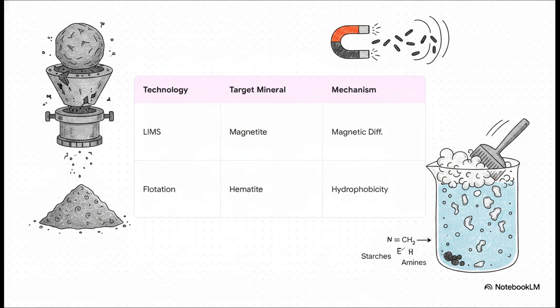Once it's ground into a fine powder, we have to separate out the iron. If it's magnetic magnetite, we just use low-intensity magnetic separation to pull it out. But for non-magnetic hematite, well, we use a brilliant physicochemical process called reverse cationic flotation. We mix the ore into a watery pulp and add highly specific chemicals. We use starches to chemically depress the iron oxides, keeping them at the bottom, while amines act as collectors that grab onto the silica gangue and float it right to the surface to be skimmed off. It's incredible. This reduces the silica content to a super tight 5 to 8% window.